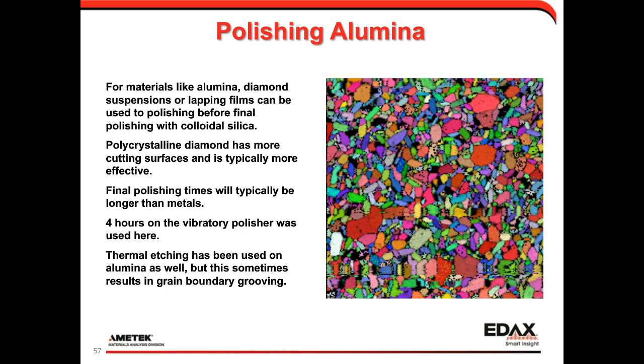When you do that, the polycrystalline diamond is generally more effective, as it has more cutting surfaces. It usually takes a little bit longer because you're having to polish on colloidal silica, and the removal rate is not as high. So in this case with alumina, I did 4 hours. Other approaches like thermal etching have been used, but this will sometimes cause things like grain boundary grooving, which causes a topographic effect that again blocks the EBSD pattern and reduces your indexing rate.